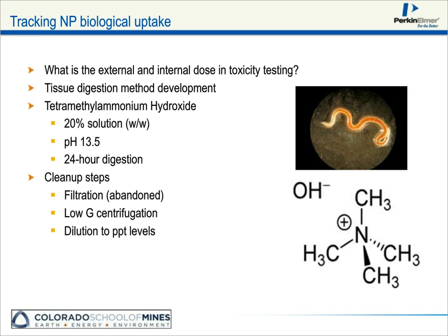So we've been working with an approach that uses tetramethyl ammonium hydroxide, that's the molecule on the lower right, and this is effective at digesting the organism. We used to try a few cleanup steps like filtration, which was not very successful. We've also looked at low-gravity centrifugation. In many cases, we can just dilute to the part per trillion levels we need, to dilute away a lot of the matrix components. So we've modified this system a bit by adding this tetramethyl high pH system.